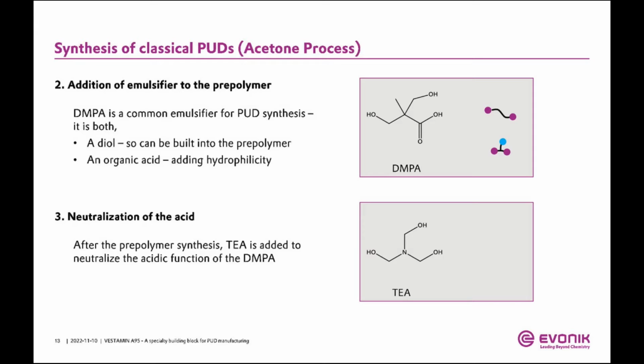So it's built into the polymer, and the side chain of the acid sticks out on the side. This acid, of course, to be later on stable and pH neutral, needs to be neutralized, and for this we usually take amines. The most simple one, or the most commonly used, I would say, is triethylamine, TEA. This is then later on added. This not only neutralizes the acid, it also turns the acid into a salt, and this salt has then even a higher hydrophilicity than the acid would have on its own.